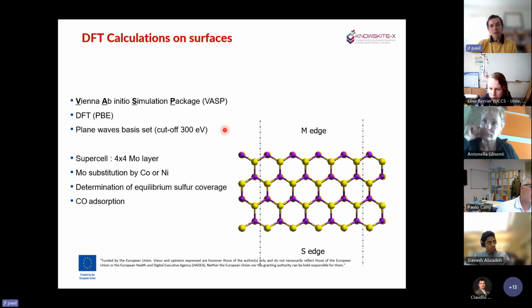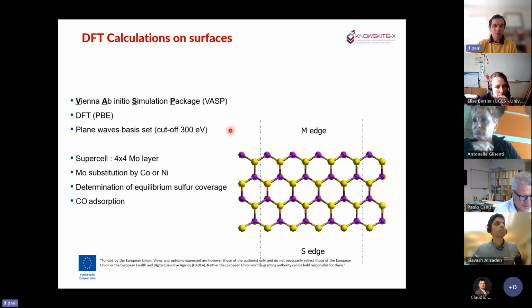And you have also the size of the basis set, and for periodic calculation, the size of the basis set is defined by the cutoff energy, and here it's 300 eV. For calculation with VASP, now you will see that people are using 500 eV most of the time, and it will give you something which is normally correct.